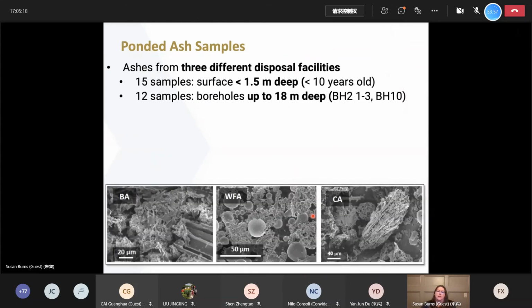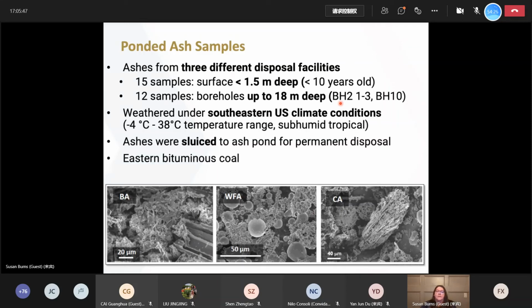So what we've done is we've sampled ashes from 3 different disposal facilities. And we took ashes that were at the surface of the ash pond. So this is about 1.5 meters deep, and they were less than 10 years old. And then we took ashes that were up to about 18 meters deep, and they were on the order of about 30 to 40 years old. So the ashes that you see denoted with BH have been weathered in the field for quite a long time. In all of these cases, they were weathered in a subhumid tropical condition. So the temperature swings were from about -4 C to about 38 C throughout the year. In all cases, these ashes were sluiced to the ash pond for permanent disposal. And the results I'll show you here came from eastern bituminous coal.